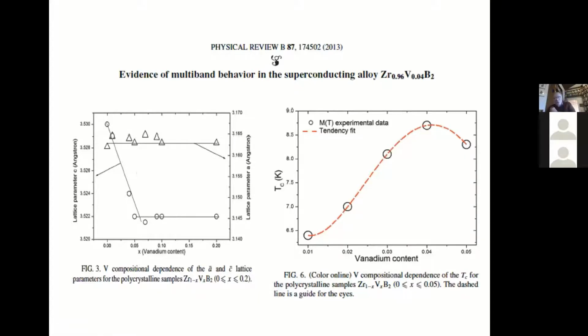In other words, zirconium diboride doesn't like to soak up very much vanadium. You have to work to get it in there, and this is just a lattice parameter versus vanadium content. And what happens is TC, you go from essentially no TC, that's zirconium boron 2, to a TC of close to 9 Kelvin. So again, you have this non-superconducting material sitting there, and you perturb it by forcing some vanadium in, and it suddenly becomes a 9 Kelvin superconductor.